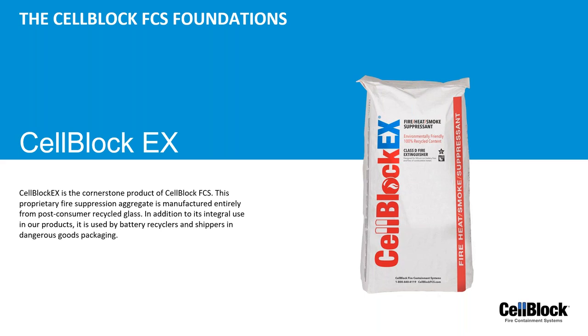But let's go back a little bit to how that heat, smoke, and gas is getting into the grain. So you have a grain that has 75% available airspace within its internal area. Well, how is this heat, smoke, and gas getting in there? A good way to understand this is that the CellBlockEX mineral is absorptive to some point. Maybe a good way to understand it is if you thought about it in terms of water absorption. So CellBlockEX will absorb 30% of its weight in water. So if I have 100 pounds of CellBlockEX, it will absorb 30 pounds of water.